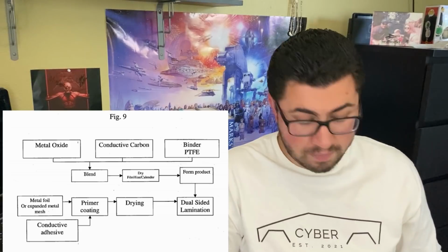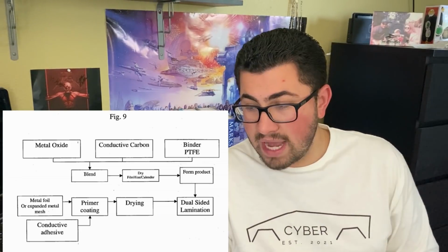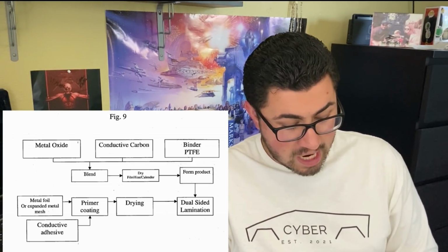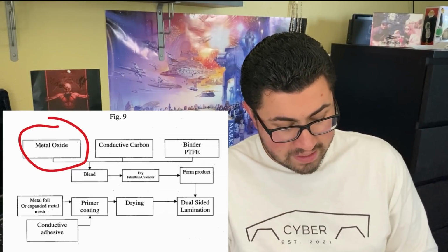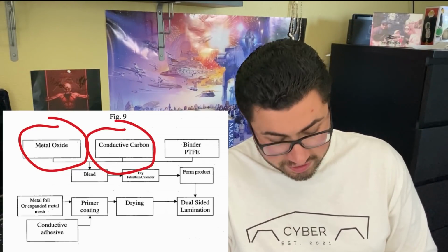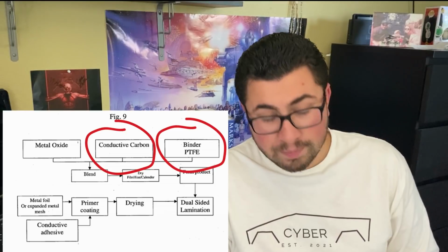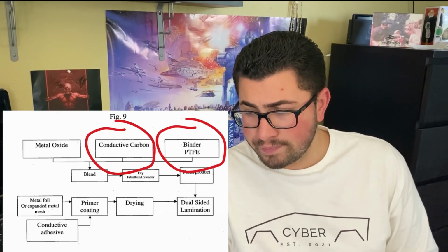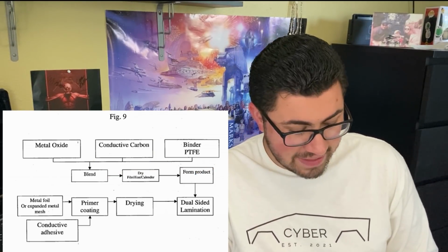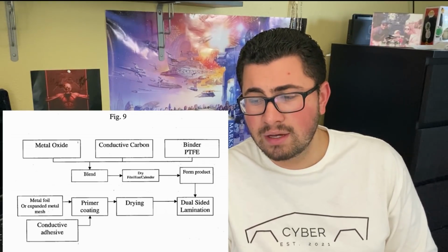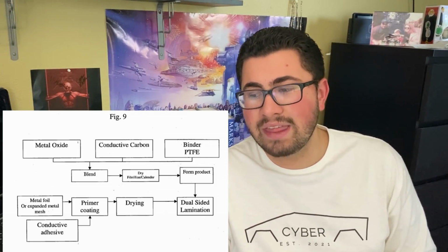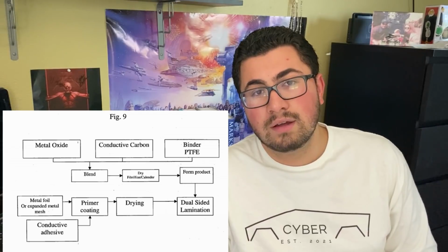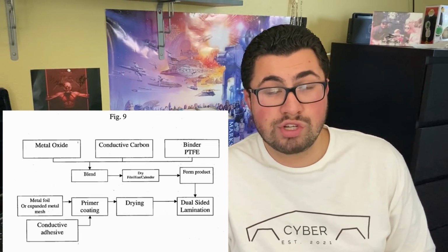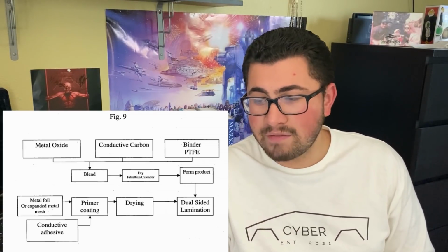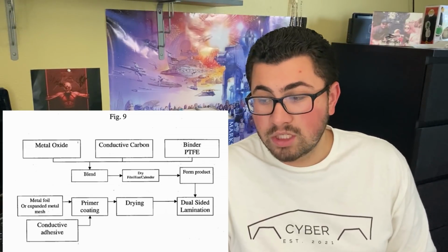So this right here is an image of the process for the cathode. As you can see, up at the top portion of this picture, they mix a metal oxide with a conductive carbon and with a binder, PTFE. The metal oxide, that's the lithium metal oxide, so that'd be something like the NMC, the NCA, the LMO, all the different types of lithium metal oxides that you can jam into the cell. That's the positive half of the cell and the positive active material in the cell.